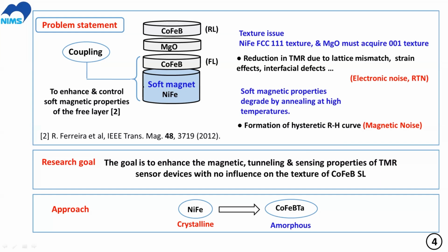So the first goal of this presentation is to enhance the magnetic, tunneling and sensing properties of the TMR ratio of TMR sensor devices, with no influence on the texture of the cobalt iron boron sensing layer. How can we do this? Instead of using the crystalline nickel iron, we will simply remove it and replace it with an amorphous phase of cobalt iron boron tantalum. Exactly what we will do is take this one and introduce some tantalum, and then we will produce a soft magnetic material, but without a template.